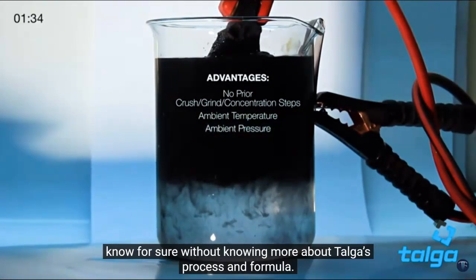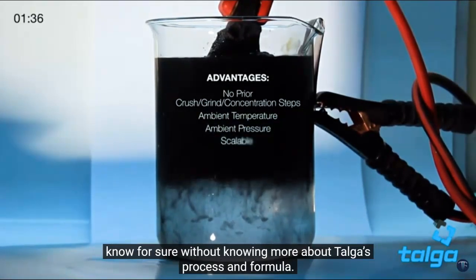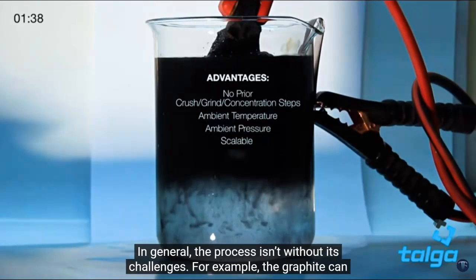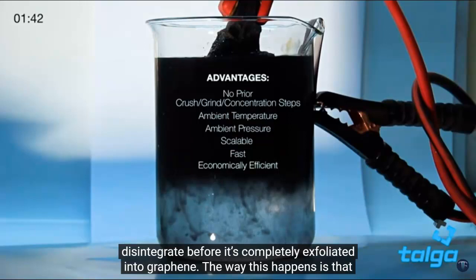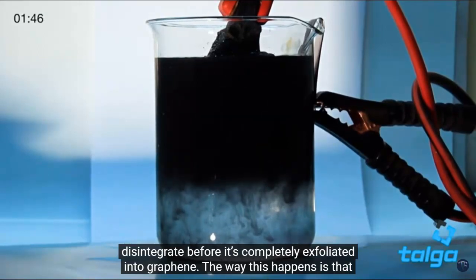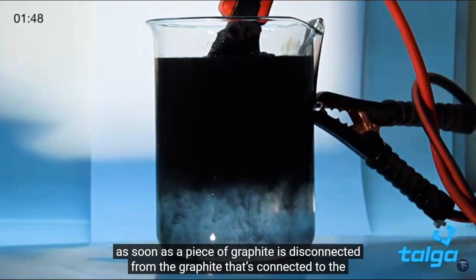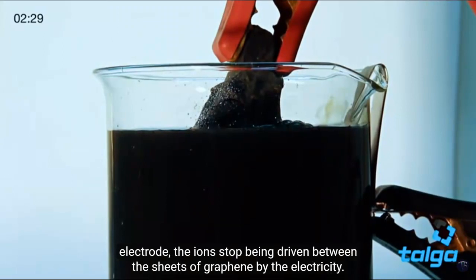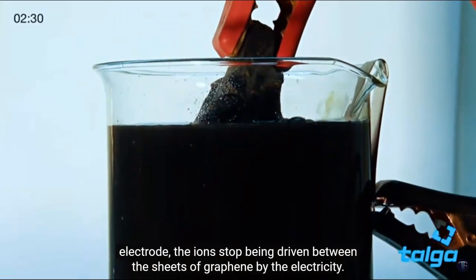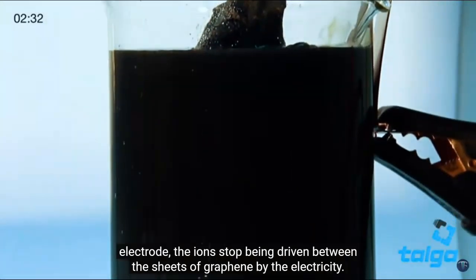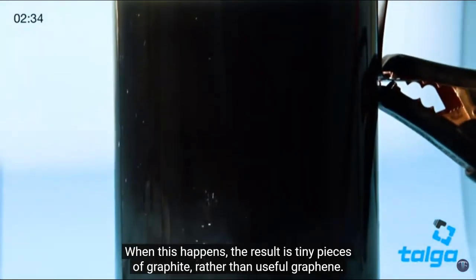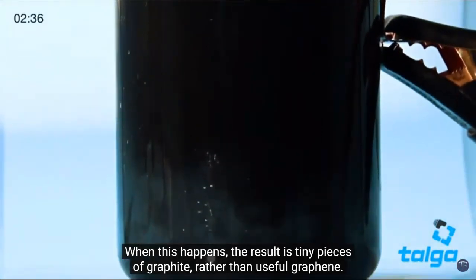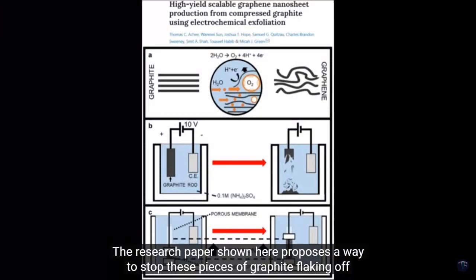For example, the graphite can disintegrate before it's fully exfoliated into graphene. The way this happens is that as soon as a piece of graphite is disconnected from the graphite that's connected to the electrode, the ions stop being driven between the sheets of graphene by the electricity. When this happens, the result is tiny pieces of graphite rather than graphene. The research paper shown here proposes a way to stop these pieces of graphite flaking off before they're finished converting to graphene.